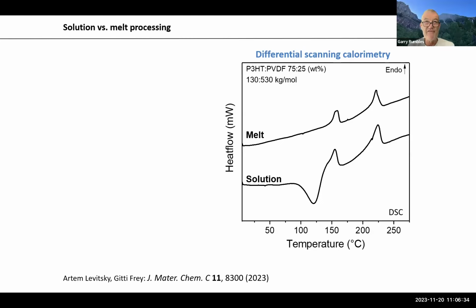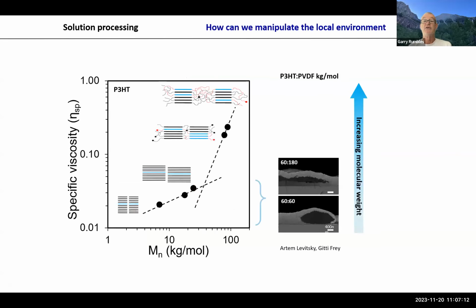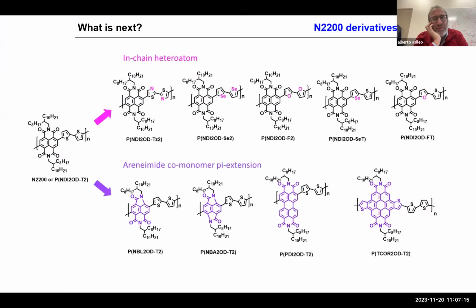Does the electrolyte have any role to play at all, other than being part of injecting the charges into the polymer in the first place? I'm struggling here. You can tell me to shut up, but I'm not understanding the full role of the electrolyte, especially when you start blending, as Natalie was doing, with polymers that allow the electrolyte to penetrate. I can see what's happening there, but I don't understand why we're ignoring the ions that are moving around. They will try to move as well, and what they do will depend.